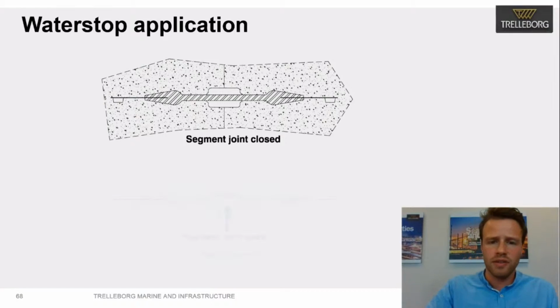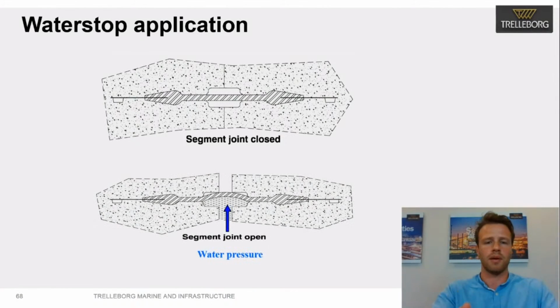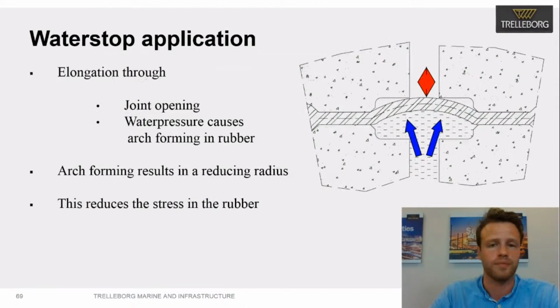So for the Waterstop application, this is what basically happens. You pour the Waterstop in, and when there is a movement, for example, when the concrete starts expanding or retracting, you will create a small joint opening in which the full rubber material starts to create an arch shape due to the water pressure in that direction. So the water pressure causes this arch forming, and it results in a reducing radius and thus also in stress decrease in the material, which is useful. That's something you want to have.